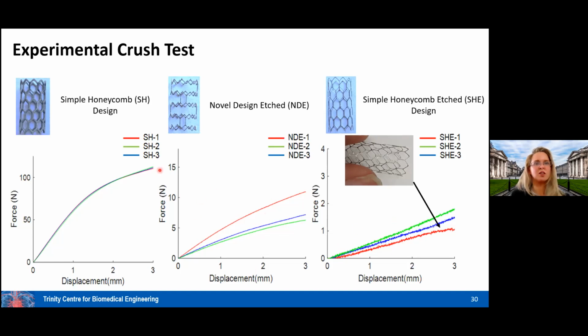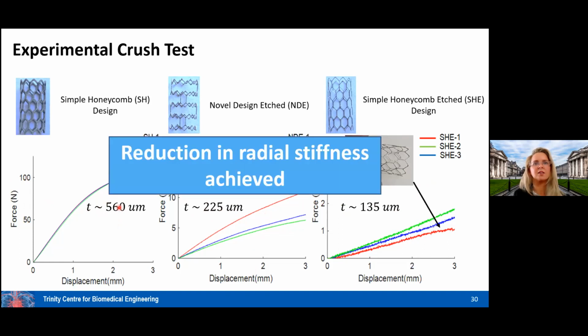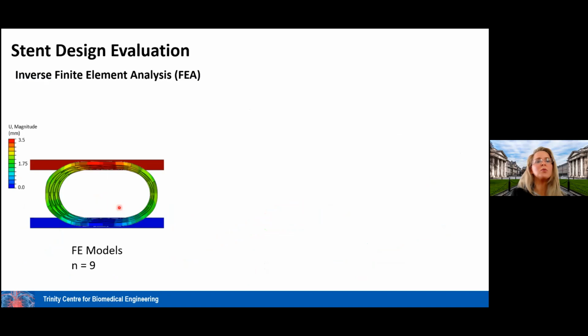Okay, and you will note that there's a full order of magnitude almost difference, or 2 orders of magnitude, going from here up to the simple honeycomb with that thicker strut. And that is down to the thickness of the struts. As you said, around 135 here, 225 here average, and up to 560 microns here on the thickness. So our reduction in radial stiffness can be achieved, and it very much just depends on the strut thickness, which is controllable through etching.